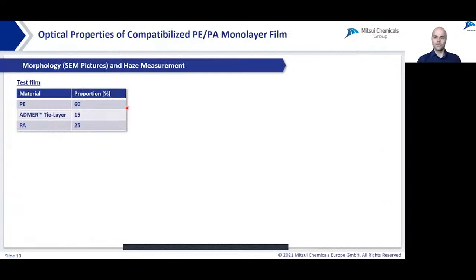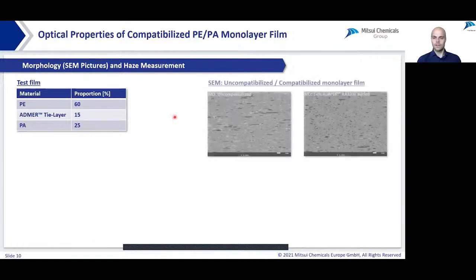As a reminder, the composition of the original film is on the top left side. And on the left SEM picture, you see the uncompatibilized sample in machine direction, with oriented PA particles in black. On the right picture, the morphology changes drastically by adding 10% ADMER RA103E. PA is better dispersed and the shape of the PA phase is more spherical-like.